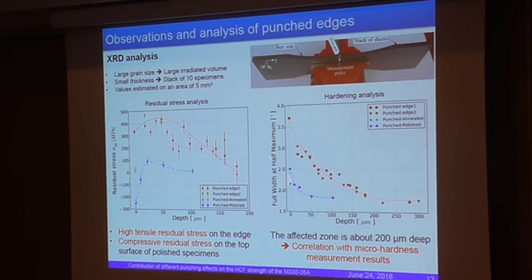And if you look at the full width at half maximum, it also gives you intel about the hardening, and you can see that it also decreases up to 200 microns. So this is the affected zone for our material. But we assume it depends also on the thickness of the material.